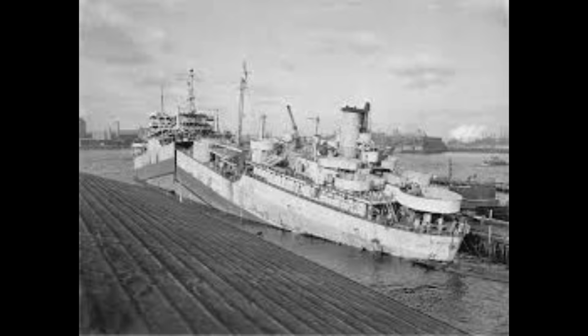The Ministry of War Transport borrowed the British-built Empire Duke for testing purposes. Constance Tipper of Cambridge University demonstrated that the fractures did not start in the welds, but were due to the embrittlement of the steel used. When used in riveted construction, the same steel did not have this problem. Tipper discovered that at a certain temperature, the steel the ships were made of changed from being ductile to brittle. The steel itself was the problem. Not the welding technique, not the workers, not the training. The fundamental material being used to build ships that would operate in cold water became brittle in cold water.